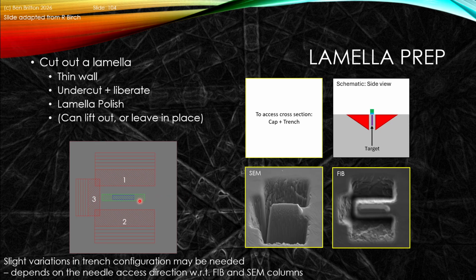In the SEM, we can see at the side angle that we've now got this thin wall that's liberated, and in the FIB we're looking down the top, and this is under the plasma FIB. We can see that we've now got those cuts. We can see the cap layer. What we'll then do is undercut, so we'll cut under here, so we can tilt the sample in the FIB to enable us to cut underneath and to cut up here, and we'll bring in a manipulator to weld. We'll liberate the foil.